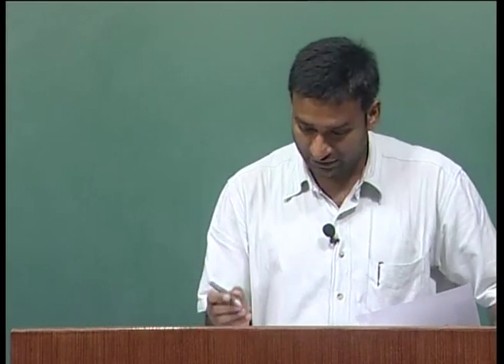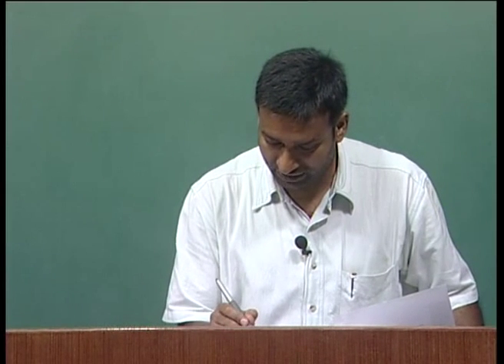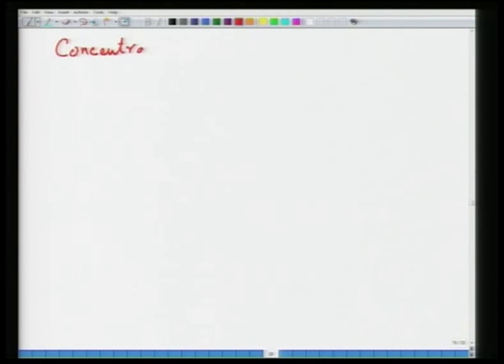You have two kinds of defect. One is intrinsic defect, which is the defect which is created as a result of either non-stoichiometry of the solid or Schottky or Frenkel defects. The second type of defect is extrinsic defect, which is created as a result of impurity incorporation in the material. So, these are two different cases. Here we will look at what is the equilibrium concentration of intrinsic defects in a given material. So, what we will do is that concentration of intrinsic defects.